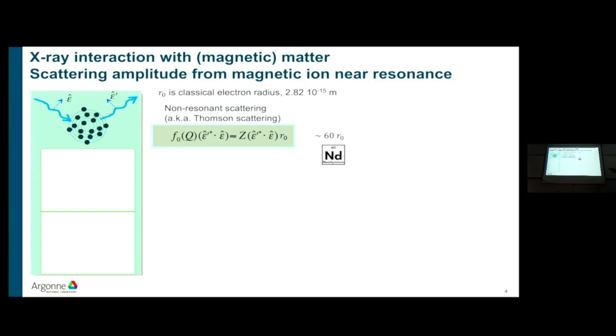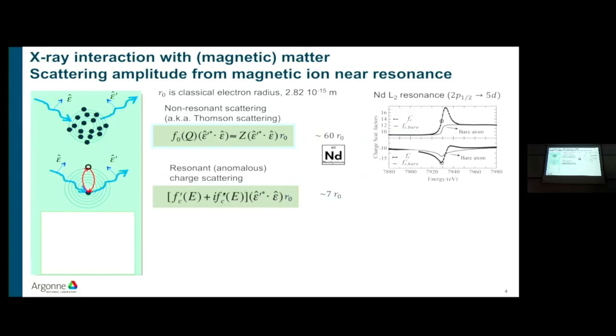So accelerated charges emit radiation, and that's dipole radiation. The polarization doesn't rotate, it keeps its orientation. And this scattering is basically proportional to the number of electrons you have in the atom. The relevant quantity here is the classical electron radius, R0. If you have, for example, an atom of neodymium with 60 electrons, the scattering power is sort of like 60 R0.